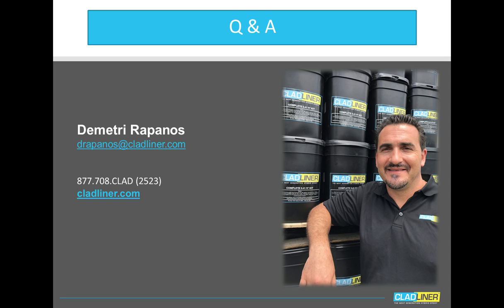It's a very interesting technology because one of the challenges we've always found with chimney seals is that they have isocyanates, so they're very dangerous to apply. They have low moisture tolerance, so they're very temperamental during application in wet environments, which is what we always found in manholes. And number 3, they traditionally do not have really good shelf lives. The Clad seal was specially developed to bridge all of those. It has a 2-year shelf life, it handles moisture in the environment, and it has no free isocyanates, making it very safe to apply, like 100% solids product in the field.